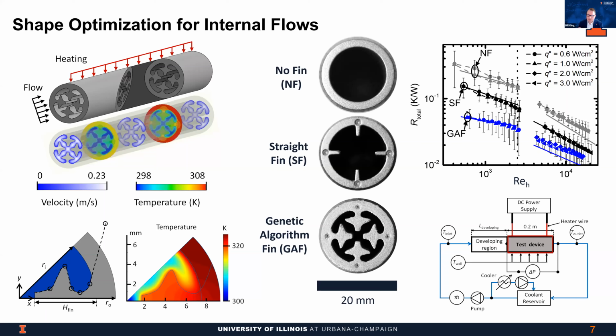If you look for heat transfer augmentation for internal flows, you see examples in applications where people will score the inside of the tube, or where they'll extrude tubes that have simple straight fins like the ones that I showed here in the middle of the slide. But what we've done is come up with a much more novel shape. And you see we get about 10x reduction in the thermal resistance for the device with this genetic algorithm fin, we call the GAF. So we designed and tested these devices.